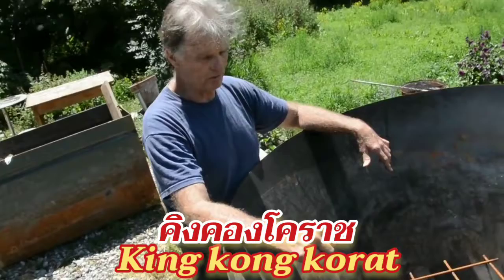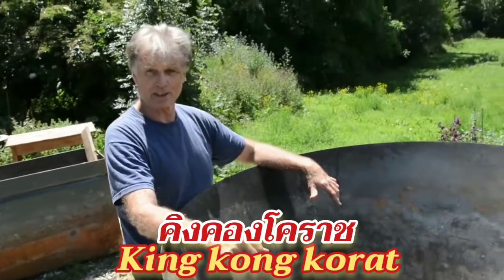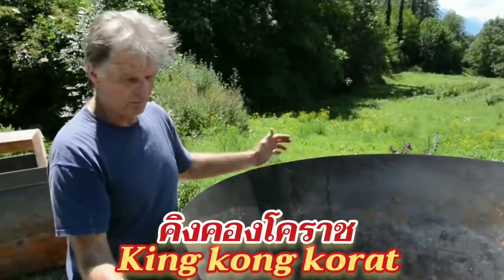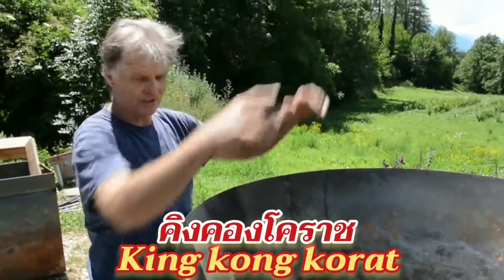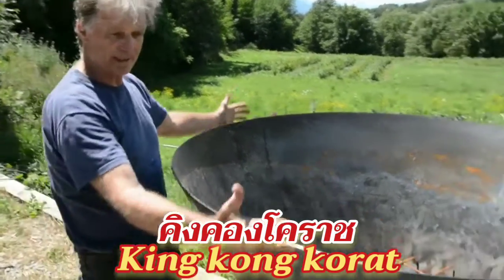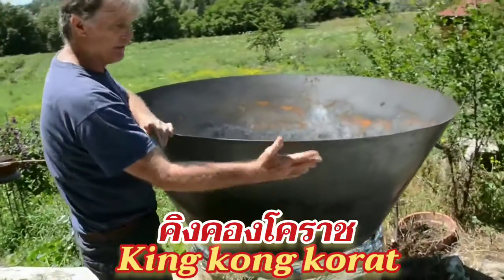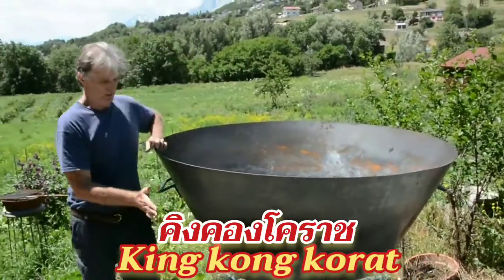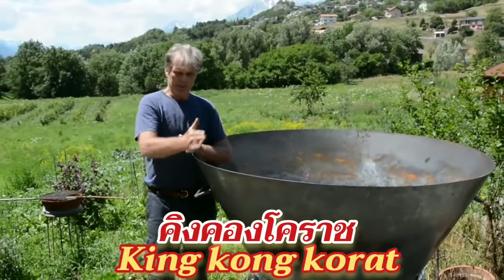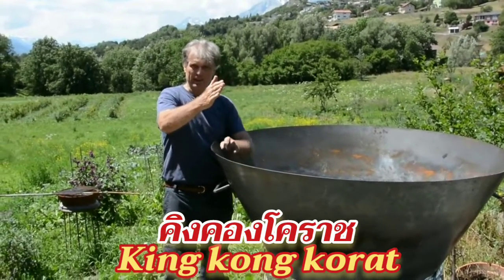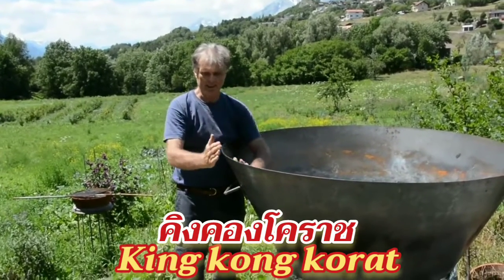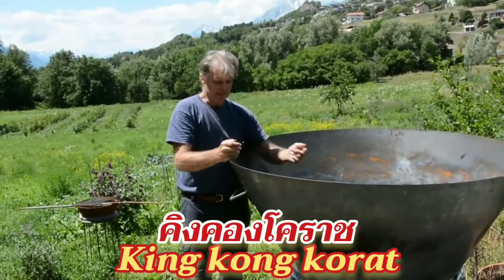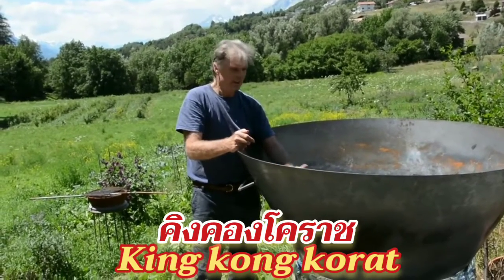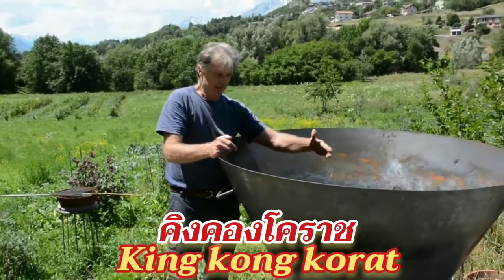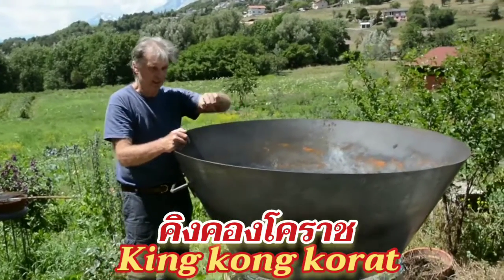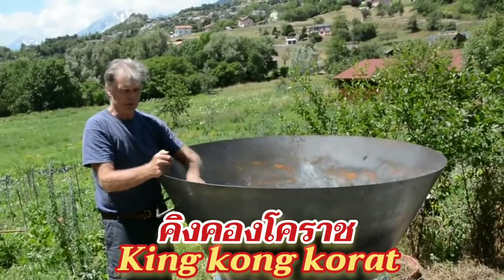I'd like to explain what we learned about how the draft works on this kiln. When the kiln is hot and there's an updraft in the center, it's pulling air up around the edge of the cone, and that air rising, even preheating a little bit, coming up around the edge of the cone, updrafting here, pulls air from the inside of the cone. So that entrains the air like this, and then that pulls air over from the center of the cone, which then pulls air down in the interior of the cone, and then pulls air across from the outside.